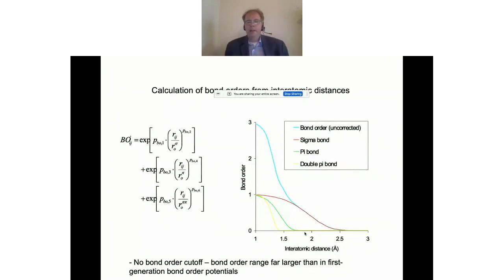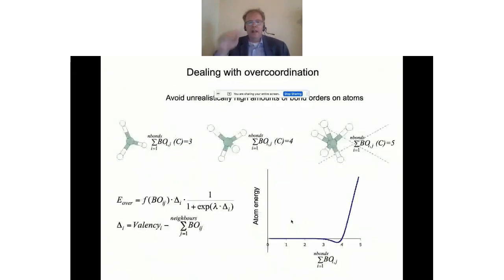So all your reaction barriers are going to be pretty much the strength of a carbon-carbon bond, which is something like 80 or 90 kcal. Many important reactions for hydrocarbons have actually much lower barriers because they're concerted reactions. When you break a bond, you essentially make a new bond at the same time. And so this long-range bond order relationship gives ReaxFF a chance to actually capture those transition states.